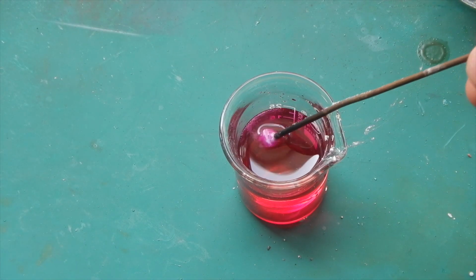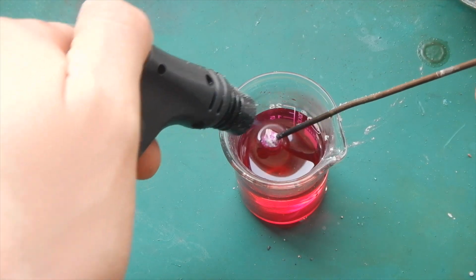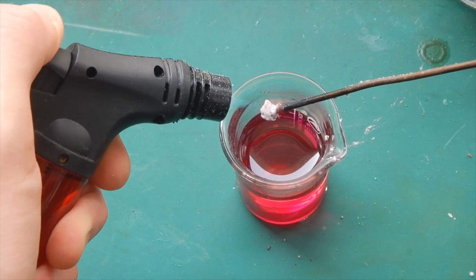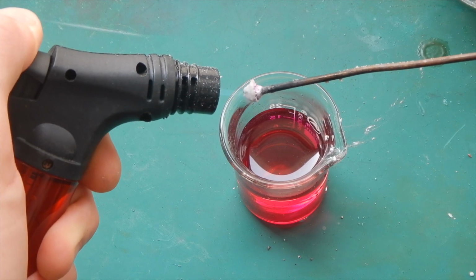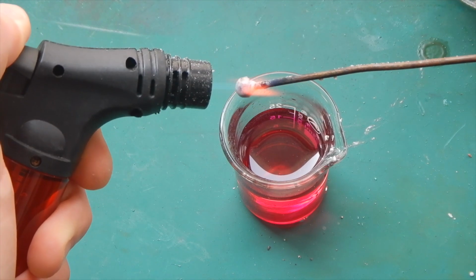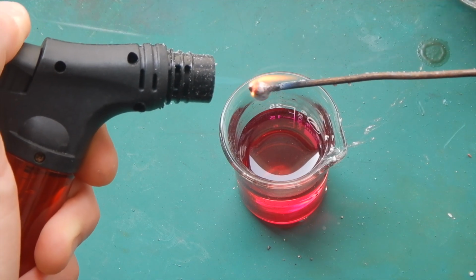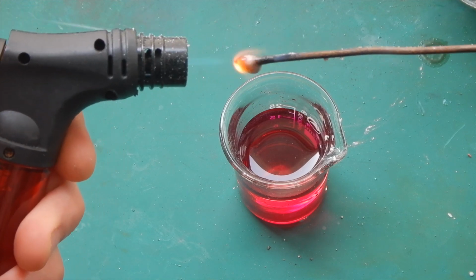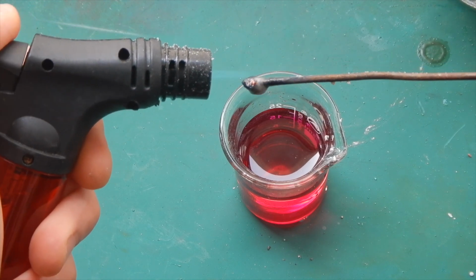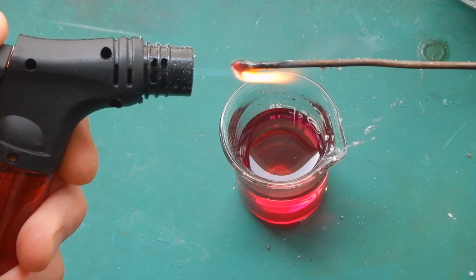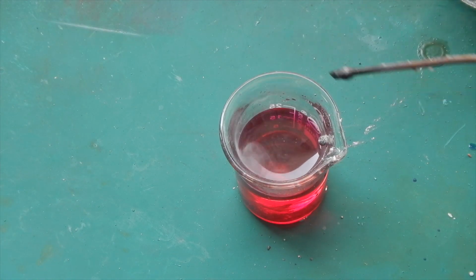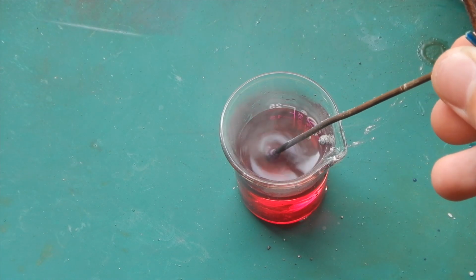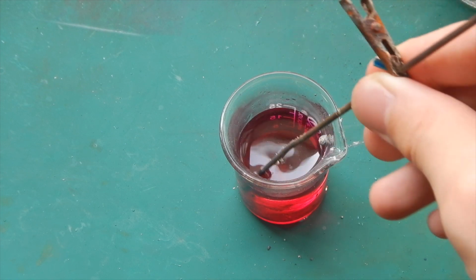I then took the lump of lithium out of the water and blasted it with a blowtorch. When the water evaporated away, the lithium let off some bursts of flames, but unexpectedly it didn't burn very easily. As I mentioned, the lithium chloride tends to stick to the surface of the lithium and protect it from air, even when it is molten. The beautiful red flame color was observed as well, which really saved my day.